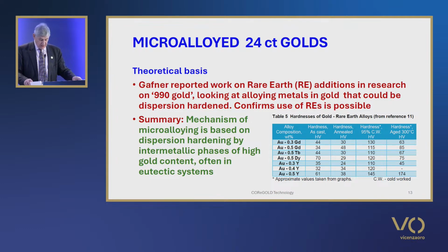confirming the view expressed earlier that in the consideration of the solubility data, the heavy rare earths suggested little age hardening was possible at these low alloying levels. Whether alloys of gold with the light rare earth metals show good properties was not known at that stage. It is difficult to comment on the results for the gold yttrium alloy, as there is no published gold yttrium phase diagram, but recent work by Ning indicates that it is similar to the heavy rare earths with some solubility of about 2% of yttrium in gold.